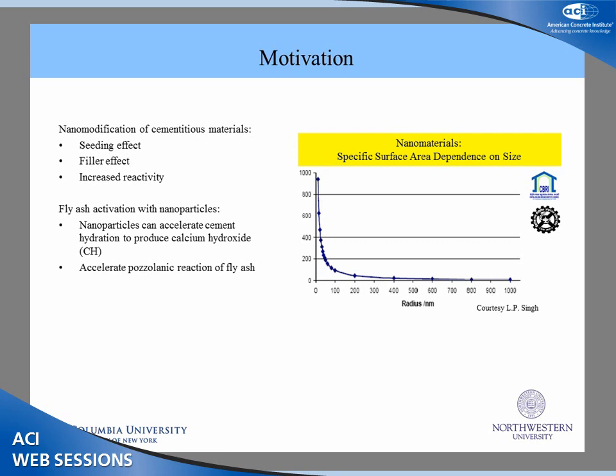And this allows nanoparticles to participate in various reactions, or various effects rather. Seeding effect, where nanoparticles help to introduce nucleation sites for CSH to grow, and this accelerates rate of hydration. Filler effects, where nanoparticles are densifying the microstructure. And also nanoparticles exhibit a higher purity, so this enables them to exhibit increased reactivity. And so all these ways, nanomodification can help to enhance the properties of our material.